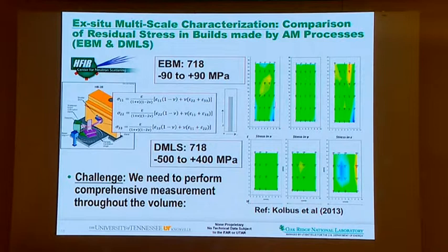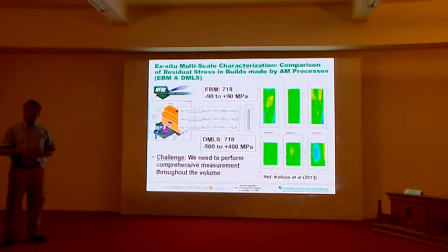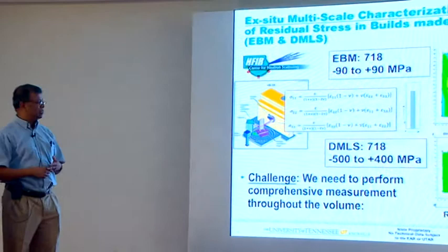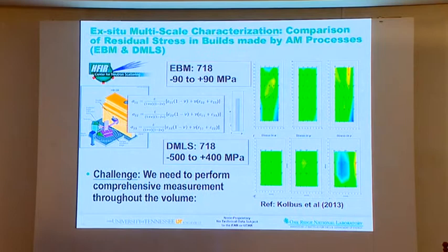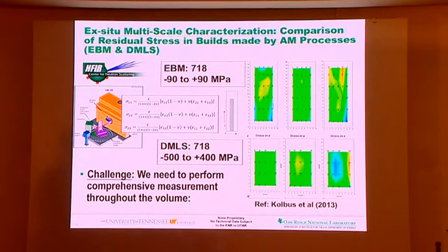For example, if you do an electron beam process, you're doing it at a very high preheat, so the thermal gradient is shallow. When the thermal gradient is shallow, you don't have a lot of stress or plastic deformation, so your residual stress is actually low. You can see that it's only plus or minus 90 megapascal. But if you're doing a laser process, even though you're putting less energy in each location, you're cooling down very, very fast, you create a lot of thermal stress and a lot of deformation, and because of that, you get a huge amount of residual stress. Again, we measure this using a technique called neutron diffraction. You can't run to this for every material, so we have to use these measurements to calibrate our computational models.